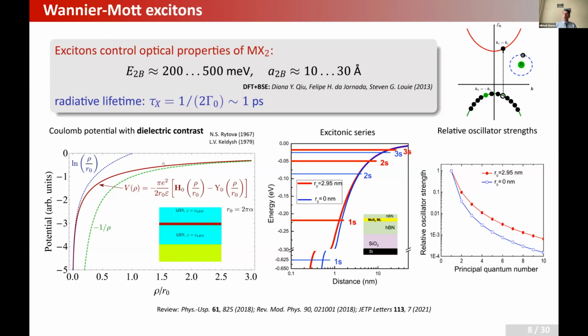However, if electron and hole come relatively close to each other, then the field becomes concentrated in this very narrow layer. Effectively, this is because of the high polarizability of these two-dimensional materials, and then electrodynamics becomes essentially two-dimensional. In that case, the interaction potential has a logarithmic form for small distances. It turns out, particularly for transition metal dichalcogenides, that the effective crossover distance, this parameter R0, is on the order of several tens of angstroms, the same order as the Bohr radius. So the effective potential can be nicely described by the so-called Rytova-Keldysh model, which was proposed a long time ago for thin films of semiconductors, but it works reasonably well for transition metal dichalcogenides.